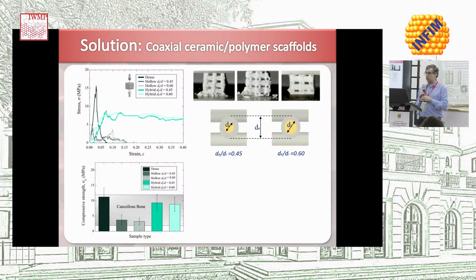So what happens when we go from the dense struts to hollow struts? Well, as you can see here, there is, of course, as was expected, a reduction of the strength. And that's simply because you have less material to support the load. So the remaining material has to withstand more stress, and therefore the final compressive strength of the material is going to be reduced. But the good thing that we found is that once you fill those internal channels with the polymer, even a weak, relatively soft polymer like PCL, you recover most of the strength you lost by going to hollow struts.